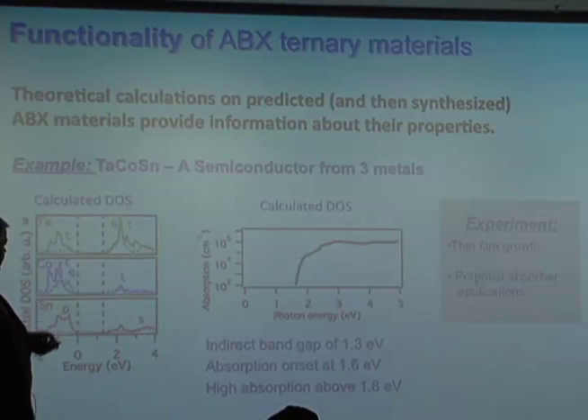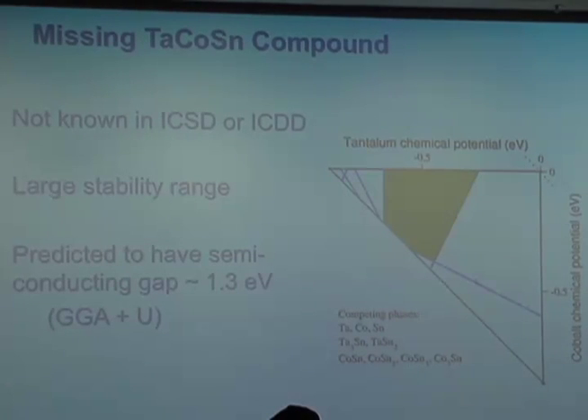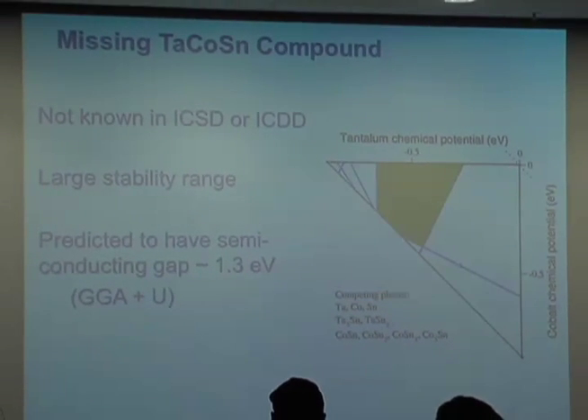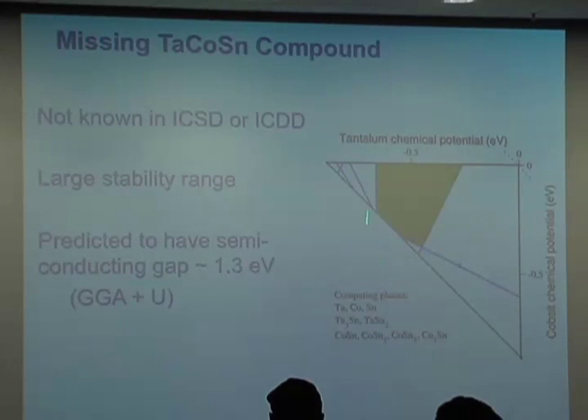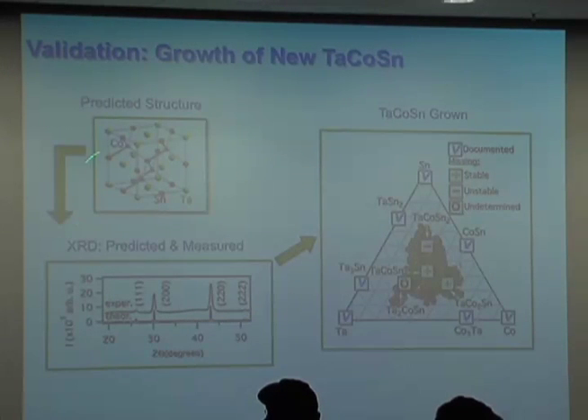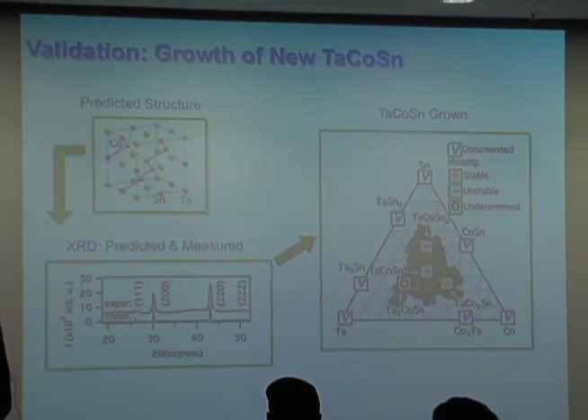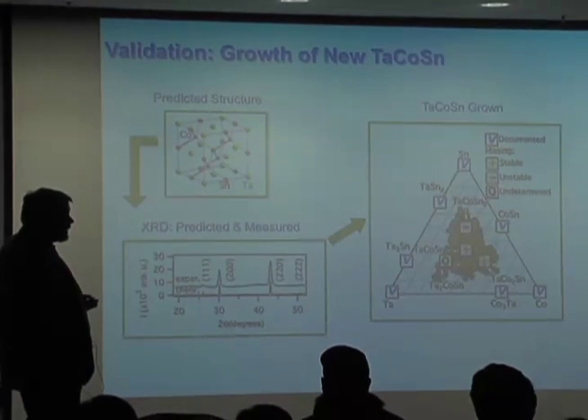And so now what we want to do is see if we can grow this material. Again, it's missing from the ICSD database. It turns out if we look at this chemical potential, there's a large stability window for it. And we have looked at all of the different competing phases, although I'll show you another one that comes up. So now we set up a sputtering system. We predict the structure, we predict the X-ray, and we use our combinatorial thin film synthesis, mapping along tin, cobalt, and tantalum. You can see where we can make this compound and see its XRD, other places where we can't make it, and other materials that are documented in the ICSD database. So this is the region where we can make this material. It turns out that we can't get a good band gap measurement of that, which was very frustrating.